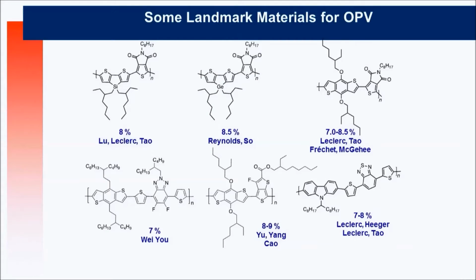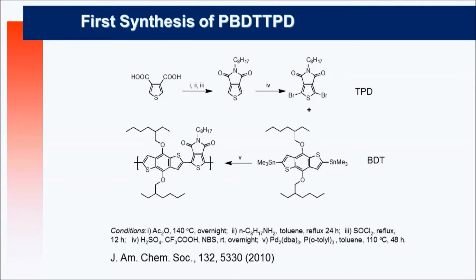Yang and Luping Yu at Chicago reported in 2009 also this very nice polymer, and now it's possible to get up to 9.5% with this so-called PTB7 polymer. And we look at it and we said, okay, that's very good, but it's not perfect. And the fact it's not perfect is because this unit, even for an organic chemist, is quite complicated to make. It's not so easy, and we're certainly not dealing with low-cost material. This unit is not so complicated, but this comonomer is. So we decided to go to this kind of structure here, where you keep what we call the BDT comonomer, and we made this new symmetric and low-cost comonomer to check or compare what we can get with this polymer. So we made, in a few steps, this comonomer here, and the BDT here.